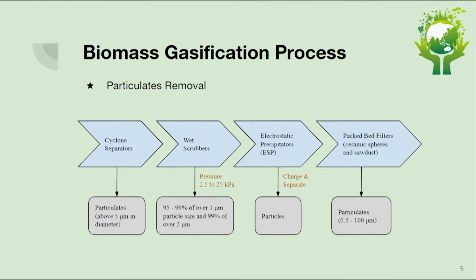Cyclone separators are taken into account to separate larger particulates above 5 micrometers in diameter at the initial cleaning stage. As well, wet scrubbers will be installed to remove particulates using liquid sprays on the gas stream. It can remove 95 to 99% over 1 micrometer particle size and 99% of over 2 micrometer particle size.